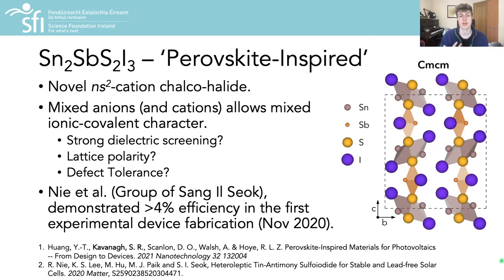Furthermore, the presence of multiple anion and cation species particularly favours mixed ionic-covalent bonding character in these materials, which typically results in strong dielectric screening. This is an effective way of reducing carrier capture by charge defects and thus non-radiative recombination.